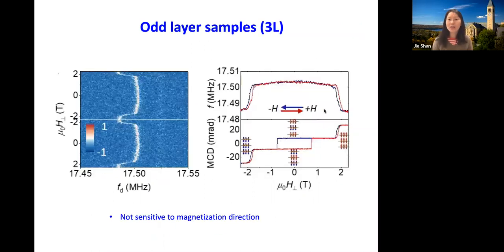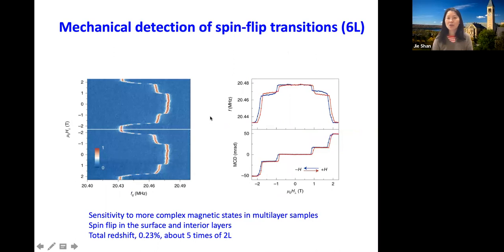And so you can test this with odd layers, and again, it's not sensitive to the direction of magnetization. So as long as the net magnetization is fixed, whether it's up and down, the mechanical resonance is not sensitive to that. And the technique is also sensitive to more complex magnetic states in multi-layer samples.